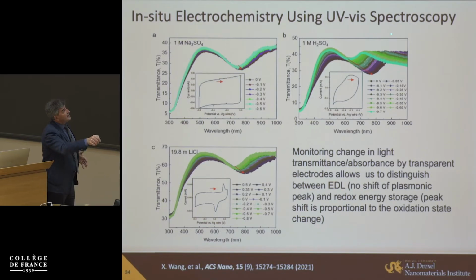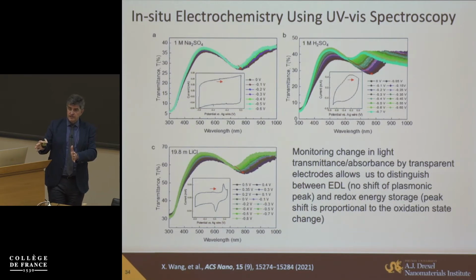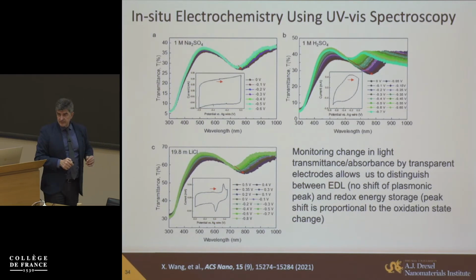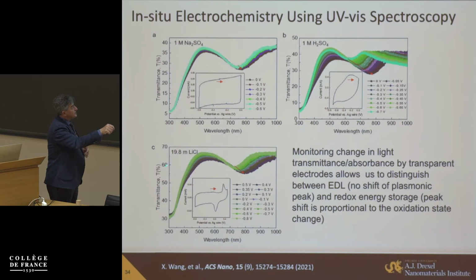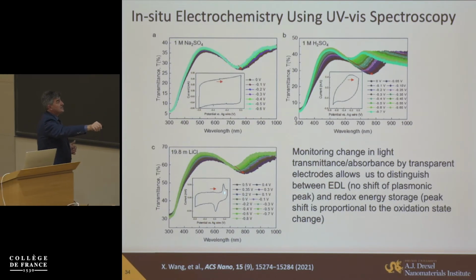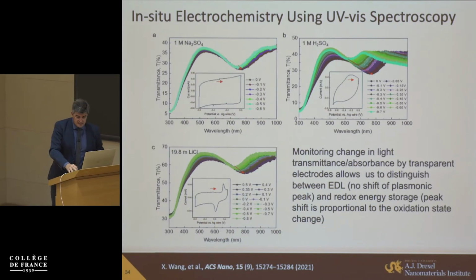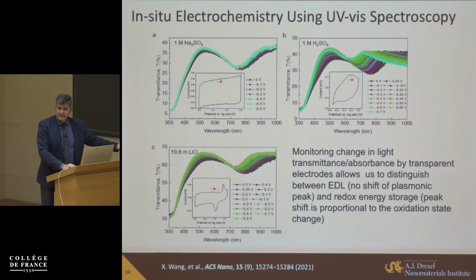And for redox, you have this major shift. If you have a combination of double layer and redox, you will have a change in the slope of peak position as a function of potential. And in this case, for example, with this electrolyte, you will get a fast change simply when ions get in, but the total change in the peak position will be much smaller, much closer to double layer compared to redox here. So we know that in this case, this was not redox. So we basically have a technique that allows us to distinguish between double layer capacitance and redox processes in materials by simply using transparent thin electrodes here.